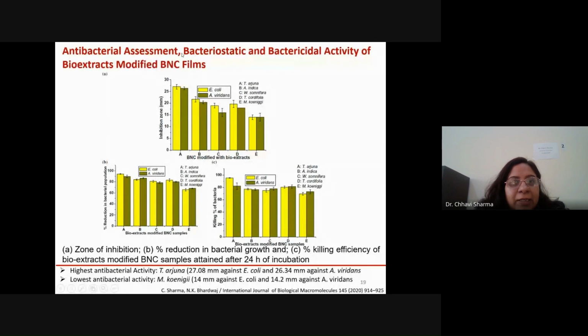Next is the antibacterial assessment. Bacteriostatic and bactericidal activity was evaluated, and it was shown that the inhibition zone was highest for T. arjuna and lowest for M. koenigii, that is curry leaf. The reduction potential of the bacterial population is also highest for T. arjuna and lowest for the curry leaf. And the same pattern is observed when we tested the bactericidal property, that is the killing efficiency of the BNC modified films.